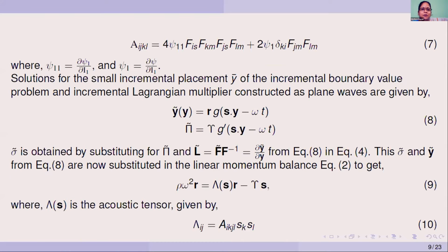Then we substitute this incremental Cauchy stress tensor and this y tilde from equation 8 back into the equation for balance of linear momentum 2 to obtain this equation 9. Here this term capital lambda, which is a function of the unit vector in wave propagation direction S, is called the acoustic tensor, which is given in its component form by equation 10.